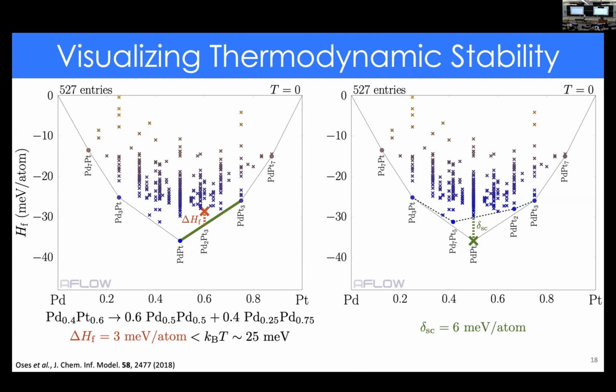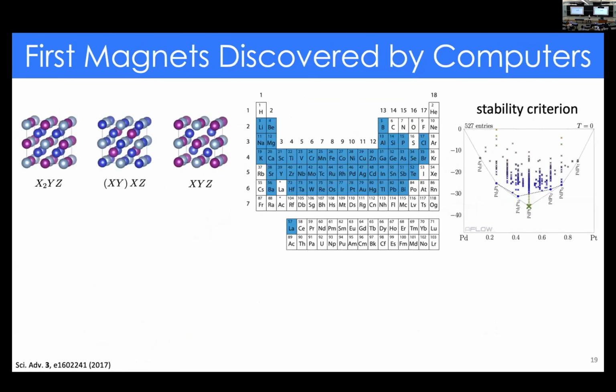You can imagine this is very well populated, so we have a lot of calculations here. But in some sense, there may be new phases that we've never thought of calculating. So what is the probability that if I find some new phase in the laboratory and calculate its properties, it's something down here which completely changes the hull, and now this point isn't stable anymore? If this distance is very large, that probability is very small. The larger that distance is, the bigger the impact that point has on the convex hull. So we want to filter for points that have a very large stability criterion. That's what we call it here. This one is 6 meV, which is not very large. We used this criterion to find new magnets.